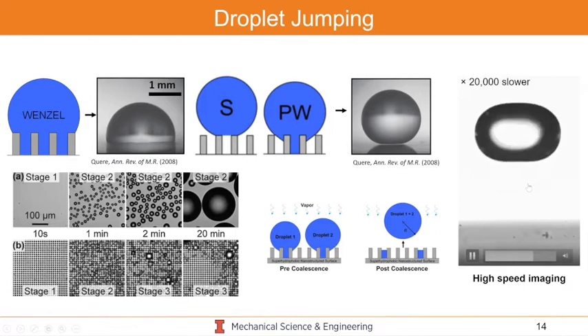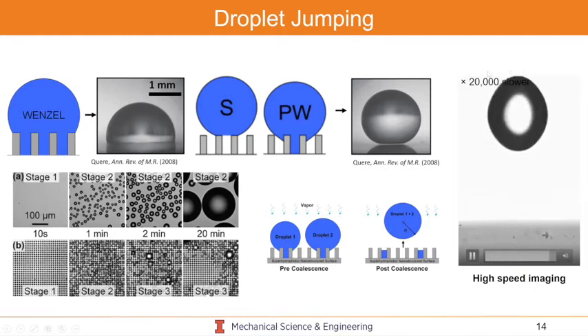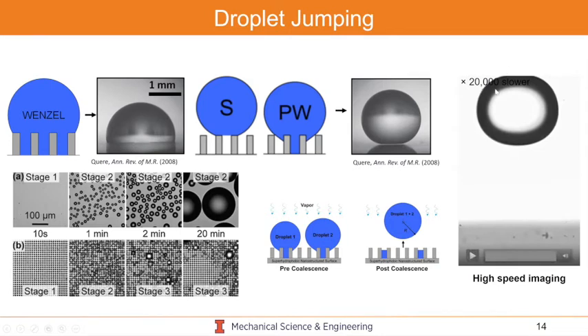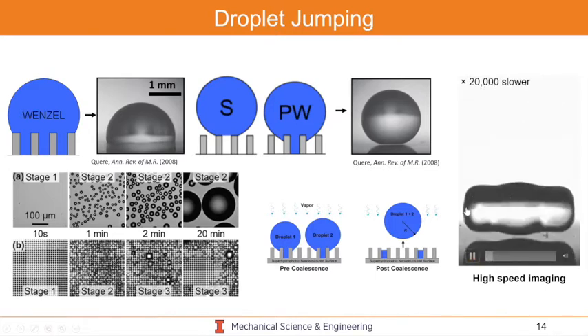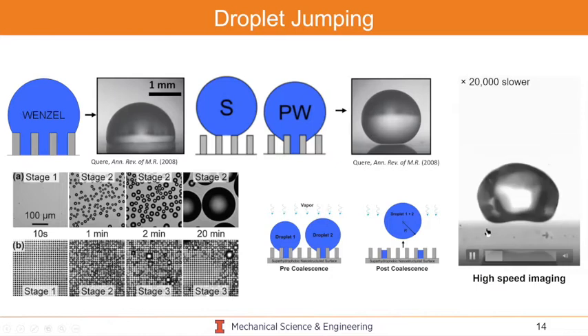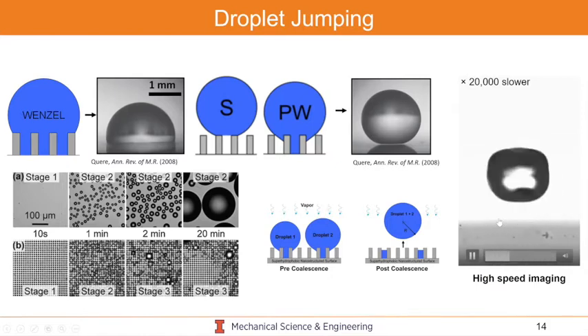It's actually not magic. Gravity's pointing downwards into the surface. And this is a high-speed video, so it's actually not this slow. This is 20,000 frames per second, so you're looking at 20,000 images per second played at you. Typically, what you're watching is about 30 frames per second. So this is highly slowed down, and so you can see the physics of what's happening. These droplets here are on the order of a couple of hundred micrometers, so they're much smaller than even a millimeter. So these are quite small.